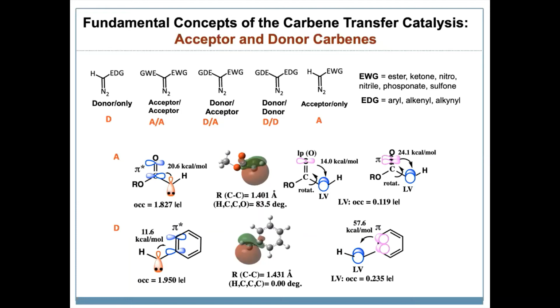But if you go to donor groups, for example some aryls or benzene ligands you put here, it also has two components: donation from the carbene center to the benzene pi star orbital, and back donation from the benzene pi orbitals back to the carbene. You can see this is almost 5 times stronger. It means the electron donating group is strong. As a result, since this pi-pi interaction is stronger, benzene rings prefer to stay in the same plane as the carbene pi orbital.